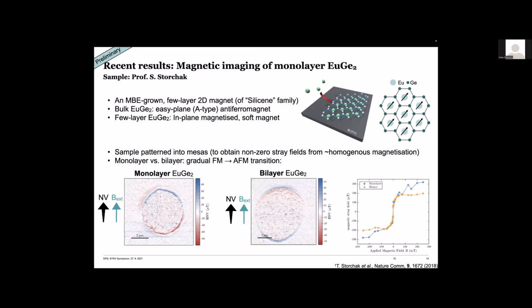Once on a monolayer of europium germanium and once on a bilayer. In both cases, this sample was patterned into this circular shape. And here you see the respective directions of NV orientation and bias magnetic field. And you see right away that while we can obviously detect magnetism, we can also see some inhomogeneities in this magnetized layer. But maybe more importantly and more interestingly, we see stark differences between the monolayer and the bilayer.